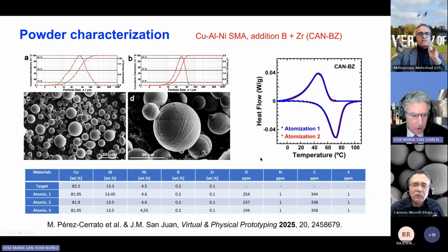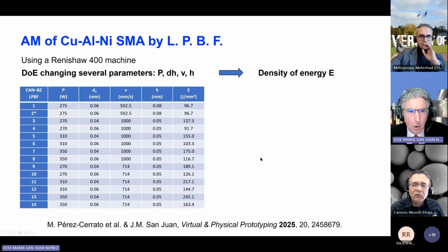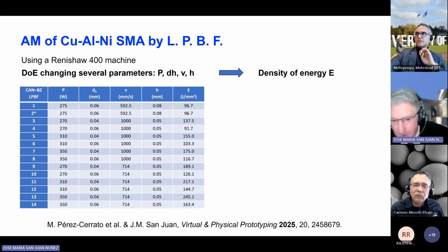So these are the powders we will use, and then we will produce the additive manufacturing by laser powder bed fusion using a Renishaw 400 machine, and using also the reduced volume setup, because, as I commented, we do not have too much amount of powders. So we have done a design of experiment changing several parameters like power of the laser, the hatch distance, the scan rate, and the thickness of the layer. You can see here the different aspects.